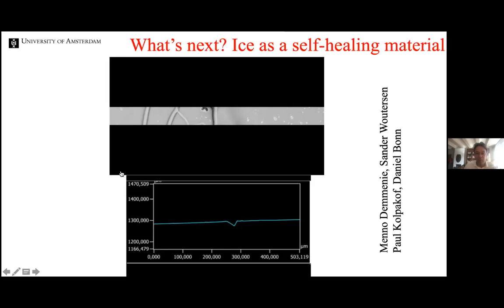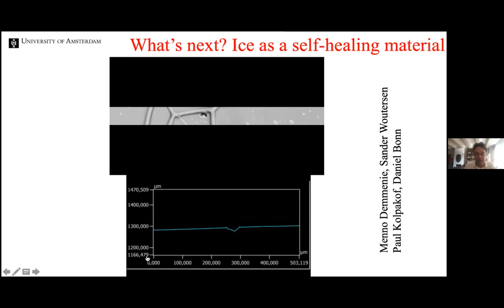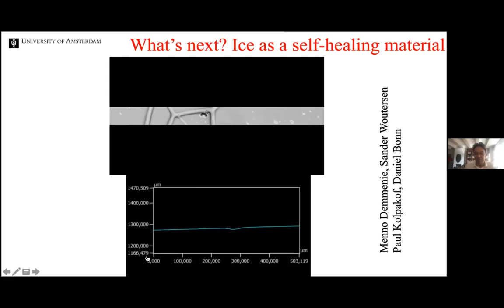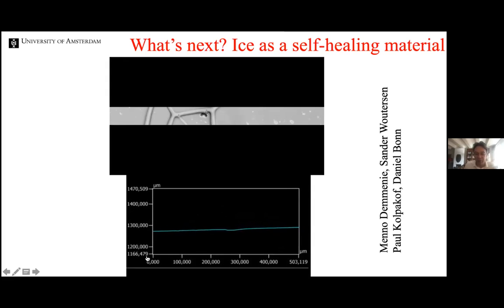So we make a scratch with a needle basically, and then over a time span of a few minutes, you see that disappear. And this is the height profile of the scratch, and you can see that it's the same scratch disappearing over time, so you can quantify what happens here, and again relate that to the surface diffusion coefficient of Kingery. So the ice part is really very interesting.